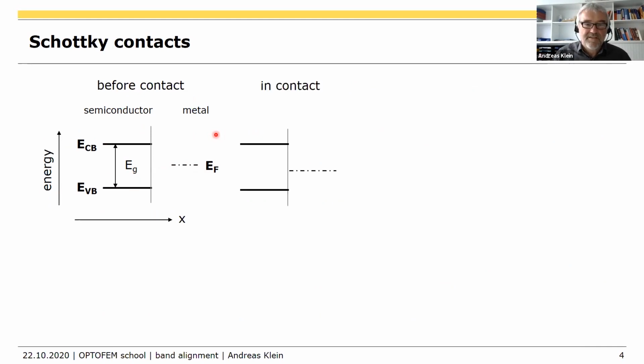If we bring that into contact, the Fermi level arranges itself somewhere inside, usually somewhere inside the band gap. And that gives us this distance, so the Fermi level position at the interface. This gives us the barrier height. So that's the barrier height for the electron. And it's the barrier height because if an electron wants to go from the metal, it has an energy close to the Fermi energy. If it wants to go to the semiconductor, it cannot go here because there are no electronic states. It has to go over the barrier. It has to go into the conduction band. So that's really a potential barrier.